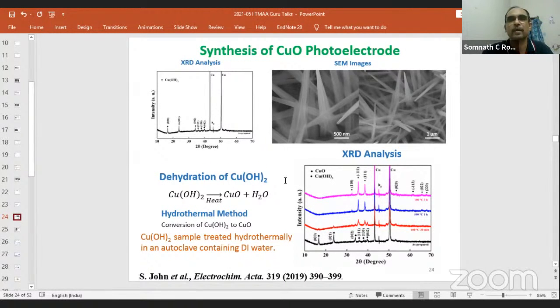It has a band gap of around 1.5, 1.6 electron volt, which means that it can absorb UV, visible, and part of the infrared radiation as well. As you know, silicon, which is widely used in solar cells, has a band gap of 1.1 electron volt. Copper oxide has a band gap of 1.5, 1.6 electron volt. Point is, when you want to make copper oxide in nano form, again, our interest, you can hardly get pure copper oxide. What happens?